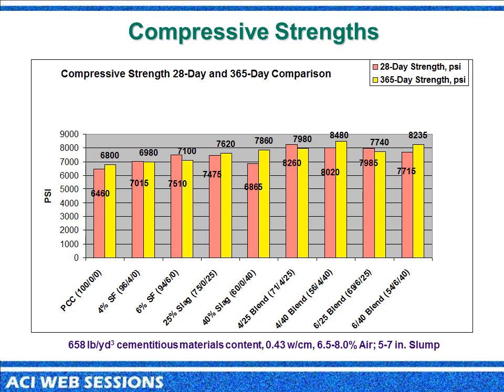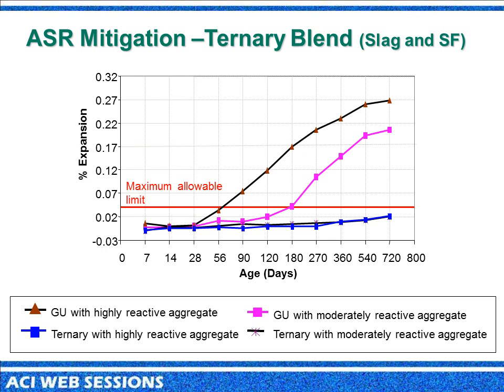But as we can see, these are typical strengths that we would imagine. Typically we might see some variation here in testing, but these are quite representative of what we would find from these blends. Now, we've also seen ASR mitigation. This becomes very important in the state of Michigan as they have a lot of alluvial sands there that can be detrimental to their pavements. So certainly, when we use these blends, we can see that we're still below the maximum allowable limits for expansion in those types of pavements.